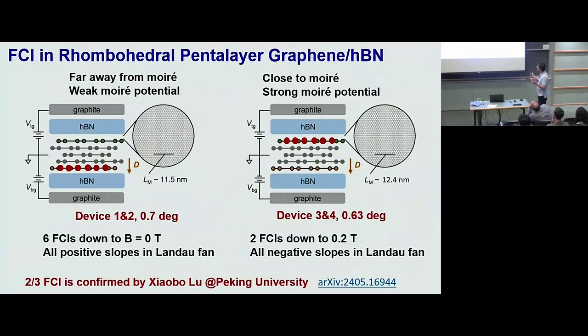So, for now, we can say this rhombohedral graphene hBN Moiré system gives you FCI in both the weak Moiré potential limit, which is when you push the electrons away from the Moiré, and when you push the electrons right next to the Moiré, where the electrons feel strong Moiré potential. In terms of experimental observation, they are quite different, right? This side has 6 states, persisting to 0 magnetic field, and all of them have positive slopes in the Landau fan. While the strong Moiré side all have negative slopes.